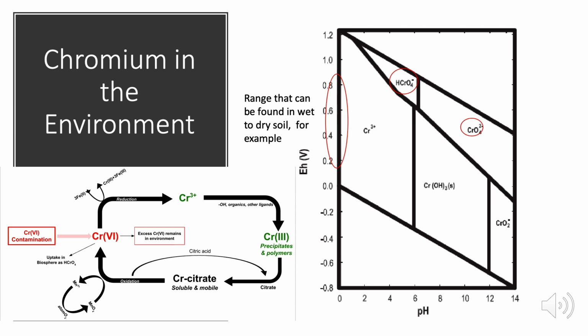So chromium in the environment is very complex. The speciation chemistry of chromium is complex. Here in this graph on the right, you can see I marked chromium-6 species in red. The formation of this hexavalent chromium depends on pH and redox potential. And in this graph, you can see that chromium-6 forms at high pH, so alkaline conditions, and when more oxidizing agents are present. But even if you have a slightly acidic soil with manganese available, chromium-6 can form. It's complex and dependent on conditions such as pH, nutrients, temperature, etc. And as you know, these vary in space, and they vary in time as well.